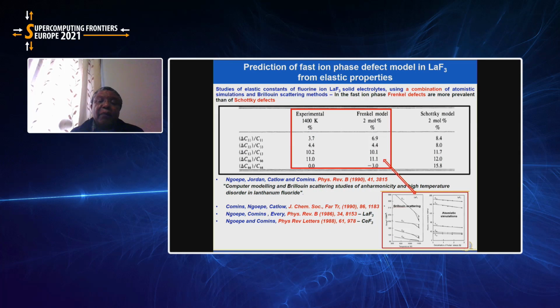And this is another example where we did the prediction of the defect models in superionic phase. These were determined from the relative changes of elastic constants obtained experimentally, and those obtained from defect models, Frenkel defect model, Schottky defect model, and we are able to say that those changes that occur here at high temperature are more associated with the Frenkel model from the simulations.